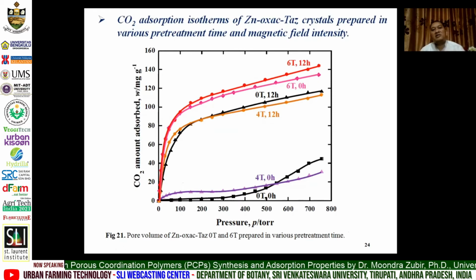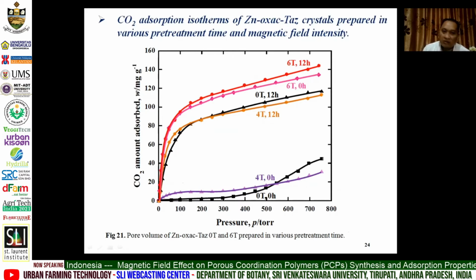And then this is the carbon dioxide adsorption isotherm of zinc oxalate TAZ. And we can check the 0 Tesla, 4 Tesla, and 6 Tesla crystals with pretreatment temperature for 12 hours and no pretreatment temperature. This is the synthesized crystal. But the 0 Tesla cannot absorb this carbon dioxide when the adsorption isotherm is measured without the pretreatment temperature. But the 4 Tesla absorbed a slight amount of carbon dioxide without pretreatment temperature.